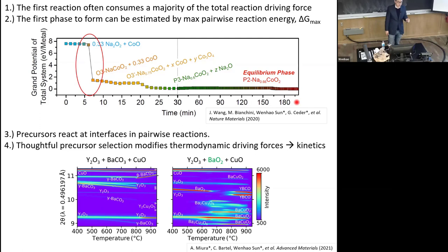So the local thermodynamic conditions govern structure selection. And I agree with you that the natural variables are not composition in that case, but really chemical potential. If you understand the chemical potential differences, and what is chemical potential? D mu dx, that's Fick's first law, that governs diffusion. Delta mu, that's the nucleation driving force, right? So all these terms in kinetics come from expressions that we don't normally see on the phase diagram. We ought to use chemical potential diagrams to interpret local solid state synthesis. So did I answer your question, or do you have more to add on that?